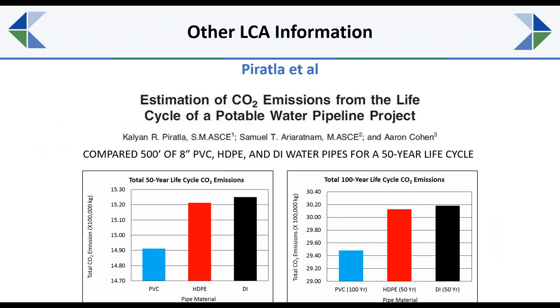The second study is from Piratla et al. And there they looked at the CO2 emissions from the life cycle of water piping. And they looked at PVC, HDPE, and ductile iron pipe. Similarly, they found that PVC pipe has the longer 100-year lifespan. But they looked at it from a 50-year life cycle, and they compared 8-inch, that smaller diameter, and they found that PVC pipe CO2 emissions were significantly less than both HDPE and ductile iron.